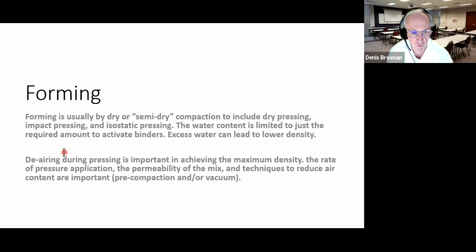Forming is usually done in these materials by dry pressing. Of course, what happens in dry pressing is you can entrap air in the body. And if air is entrapped in the body, when you eject the part from the die in pressing, it can tend to grow a little bit. That's called springback. Okay, increase in volume a little bit. So there are a lot of strategies to try to prevent entrapped air. One is to have a more permeable matrix phase so that air can get out.